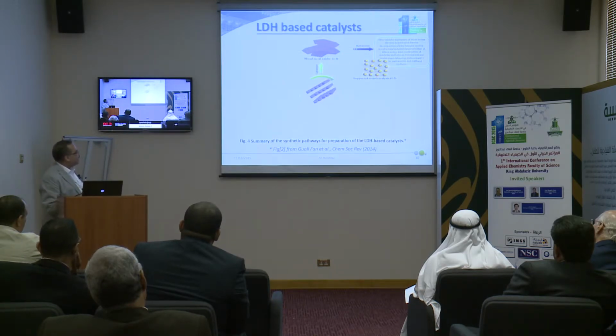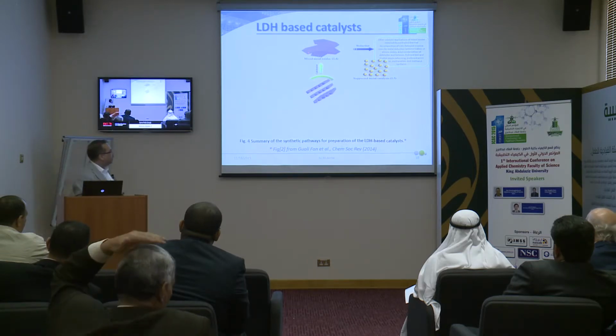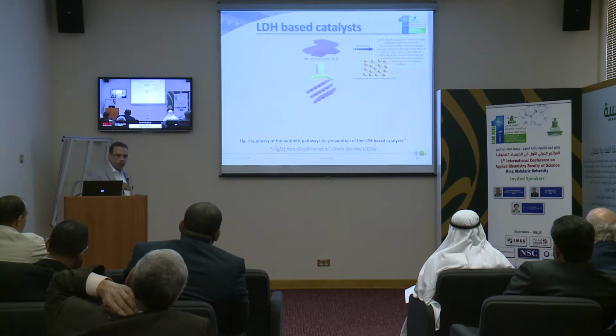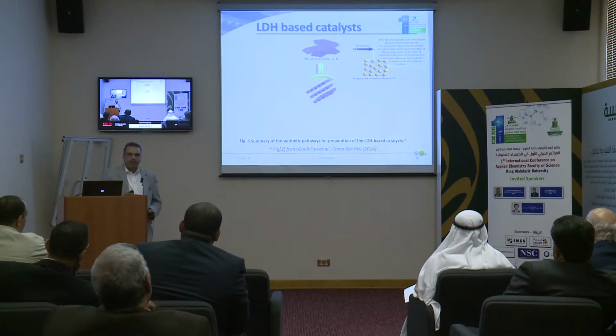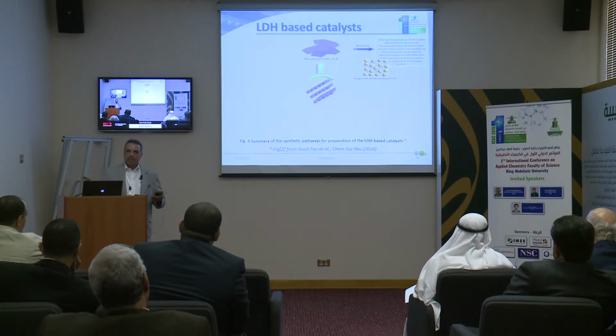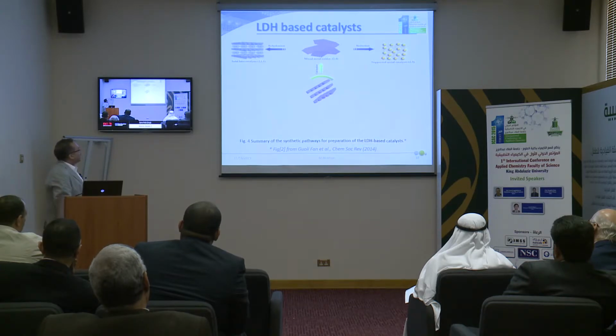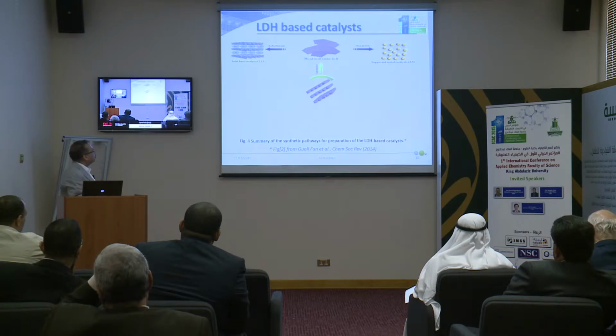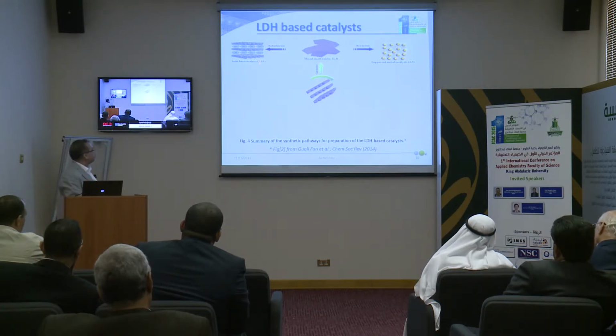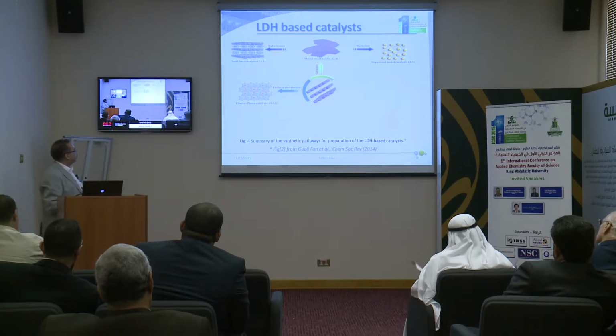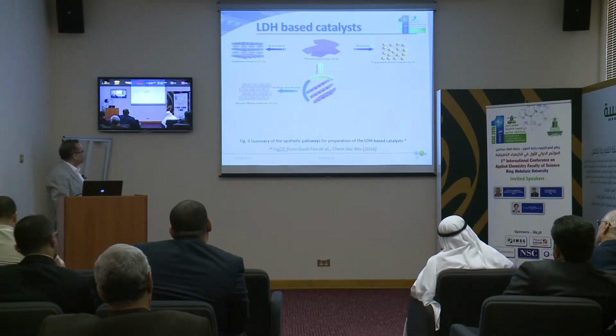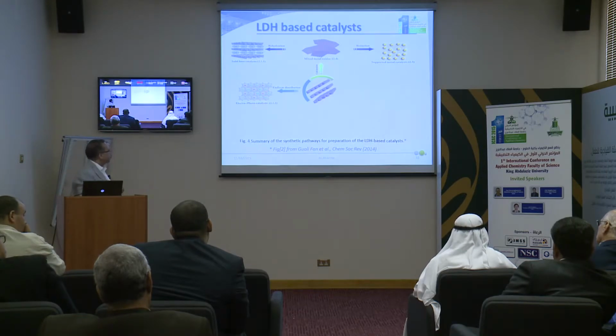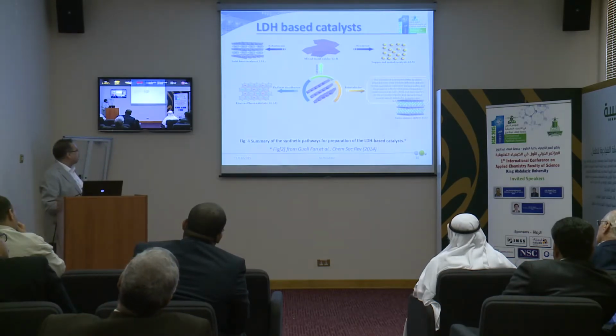If you reduce the metals in the layers itself, after calcination, you have supported metal directly on the layer that you already formed. So you don't need to prepare the support and then do impregnation of the material, then reduce the material itself. So you can self-synthesize one and only one material, then you control it later on. And this gives an advantage for the application of such material. Again, rehydration of the material introduces some terminal hydroxyl groups which have more pronounced basic sites, or you can do uniform distribution. So you can have electro-photo-catalysts, which are used in catalysis as well.